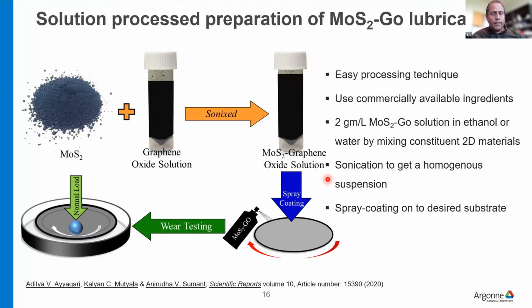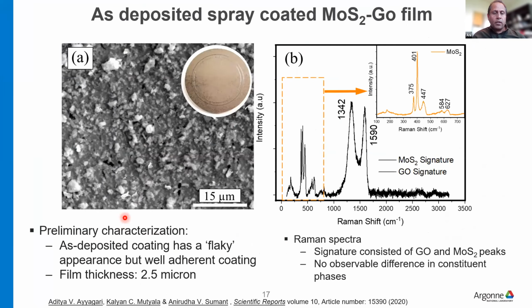So how it works: we take the MoS2 nanopowder, combine it with graphene oxide solution, do the sonication, and then just spray coat it onto the substrate surface. So this is how it looks like in the SEM. It's about a 2.5 micron thick layer, and this is how the Raman spectra look, with the typical MoS2 signature and the typical graphene oxide signature.